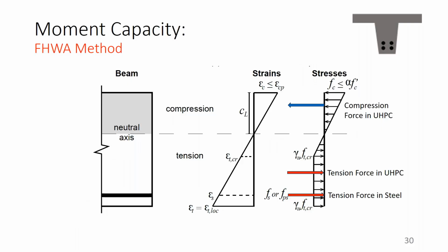Because again, we were concerned about this. We hadn't done this before. We were a little worried about it, and so we also compared to the FHWA method, even though it hadn't been approved, which is also based on compatibility. This is a hand method, which is very similar in a way to the moment curvature relationship I got before, but in a simplified way. You have the tension in the steel, the tension in the UHPC, the compression in the compression zone. You check for equilibrium and then get the moment capacity. So I won't elaborate because these are basic calculations, but I'm happy to answer questions about this later on if you'd like me to.